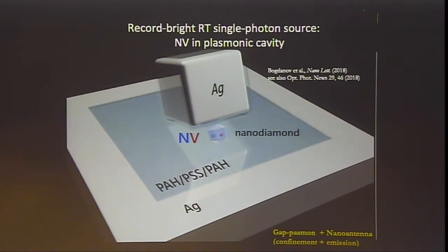But we're using for this an antenna. We're talking quite a bit today with my colleagues in ECE about antennas. Antennas are important. So what is the trick here? We use so-called gap plasmons. Gap plasmon excitations occur between two metallic structures in a dielectric gap. And in this case, electromagnetic energy is confined within this gap, which could be very small, as I pointed out. So we use this epitaxial silver film, and we use this relatively large silver antenna.